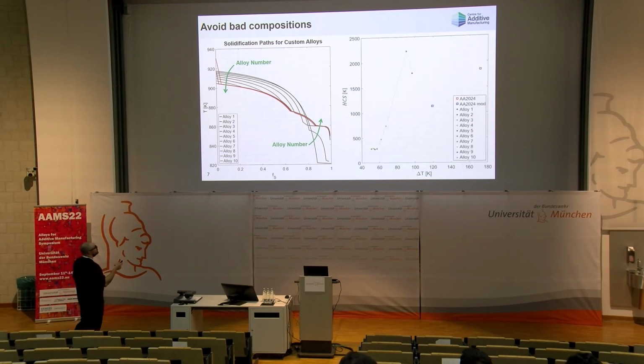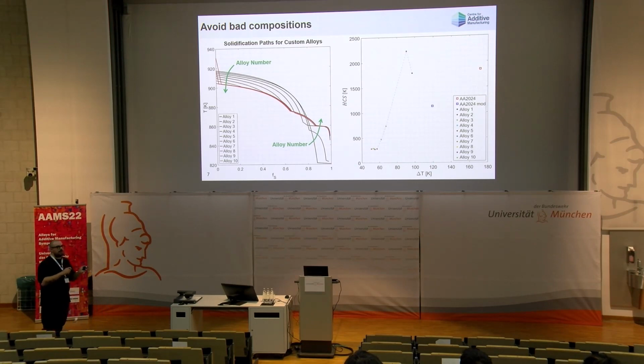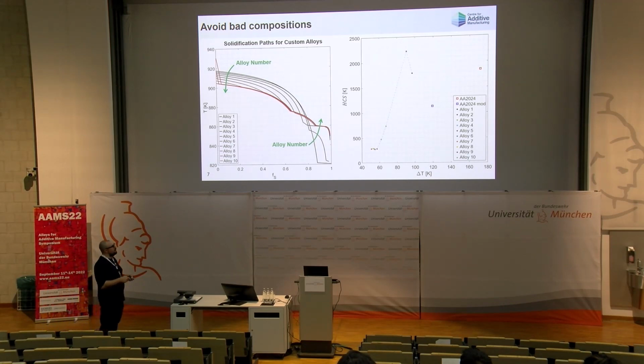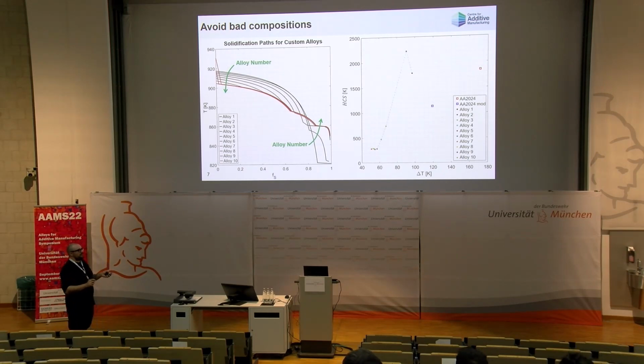Then we compute HCS and solidification range, and we compare them to data that we already know of 2024, and also modifications of 2024 made with this alloy design approach, which gave us very good results. But we wanted to be a bit more sure about the design map, because we saw some variability as a function of process parameters. So we wanted to bring these as fast and as high power as we can, so that it is industry relevant. So we are here in this zone at the moment.